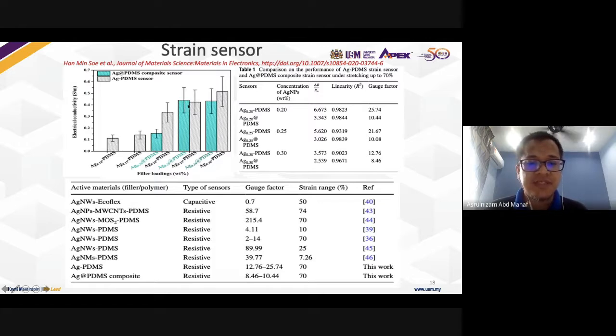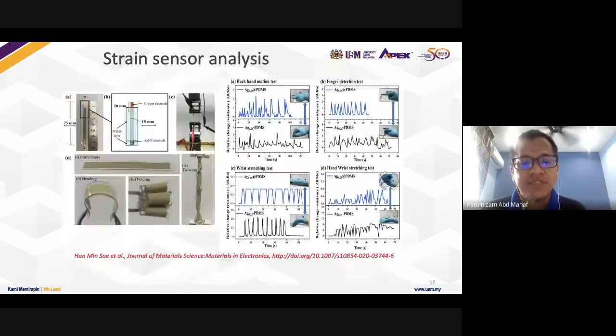With those factors, we actually got some good gauge factors, and the strain range can be up to 70%. But for the latest stretchability, last week we had a keynote talk from Prof Malaya reaching 1000 percent stretchability. It's very good, and we only have 70%. Of course, you need to play around with the material properties. So this is what we tested.